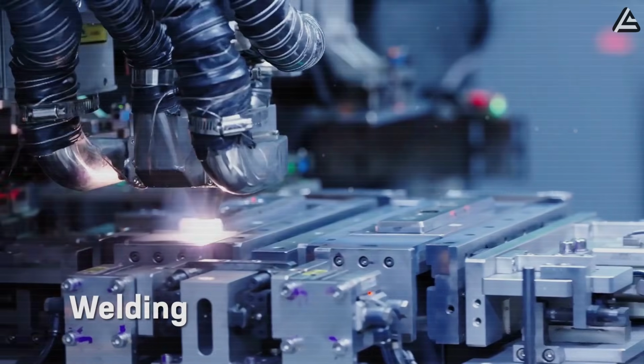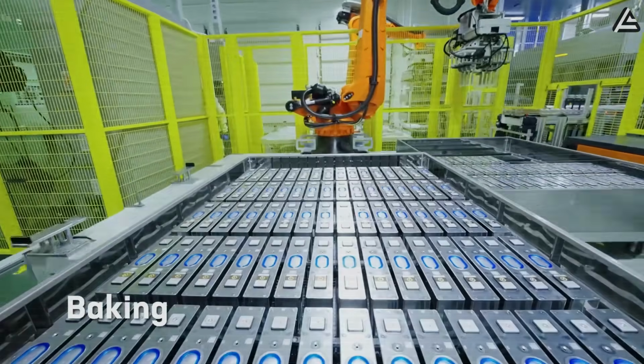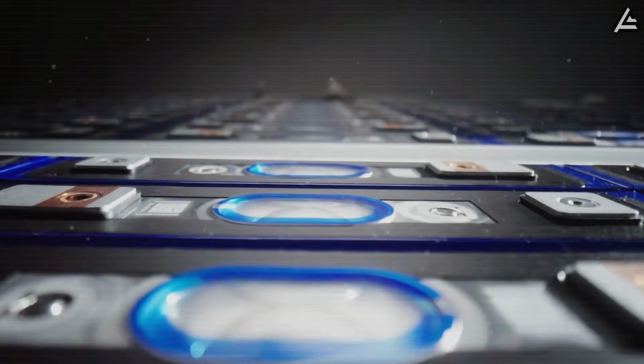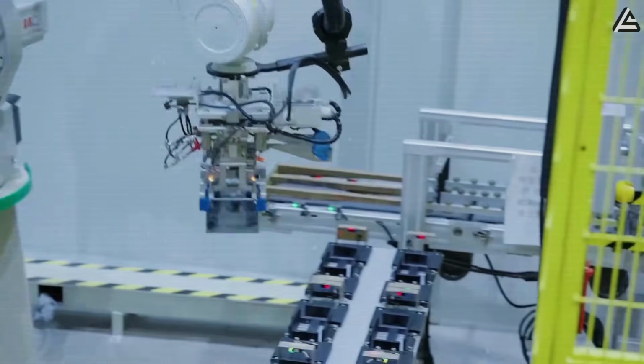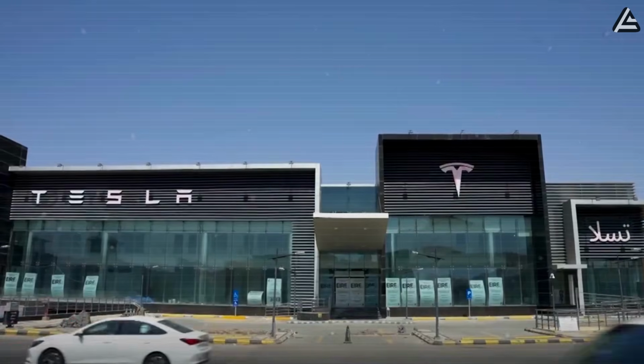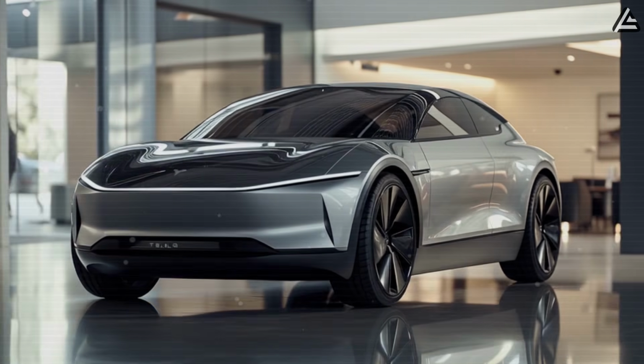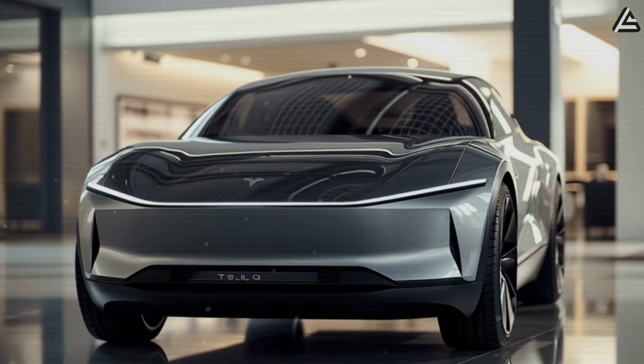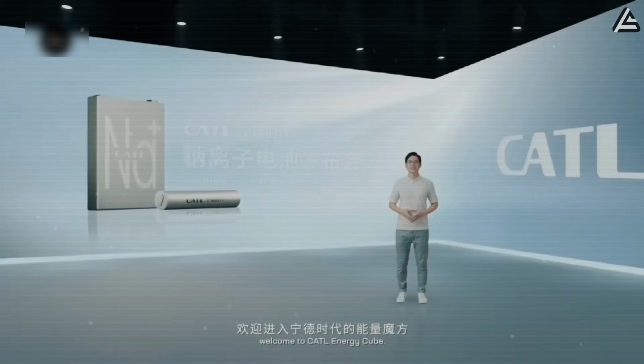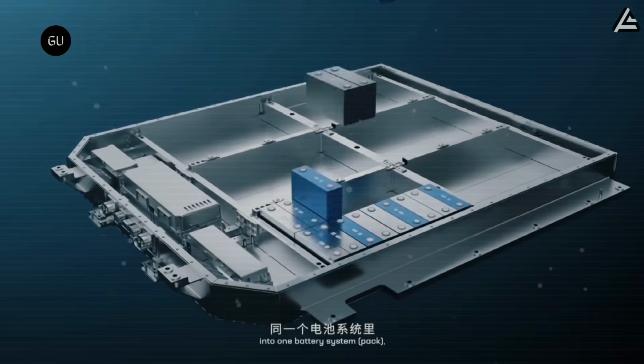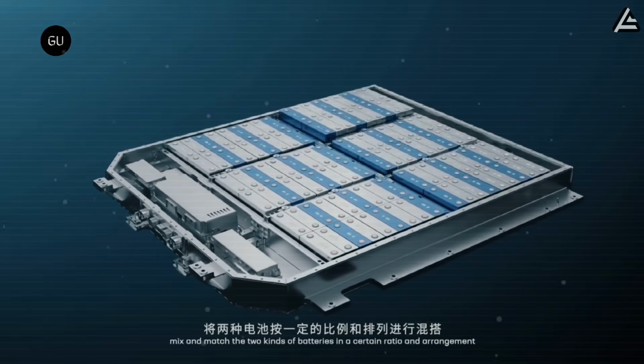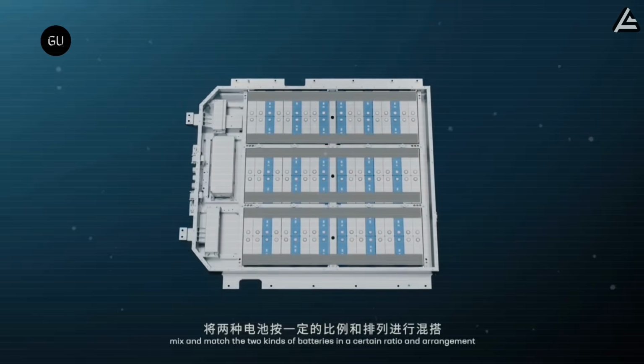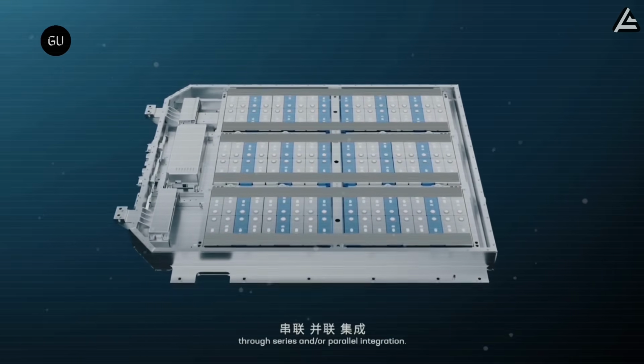The industrial rollout also shows scalability. CATL has pledged to expand sodium-ion to 30 gigawatt-hours per year by 2026, enough to supply more than 600,000 entry-level EVs. For Tesla, the strategic case is compelling. A $25,000 Model 2 will likely carry a pack in the 40 to 50 kilowatt-hour range. If sodium-ion achieves even 120 watt-hours per kilogram, which CATL already demonstrated, a pack of that size could weigh 350 to 400 kilograms, comparable to today's LFP-based Model 3 packs, but built from far cheaper raw material.